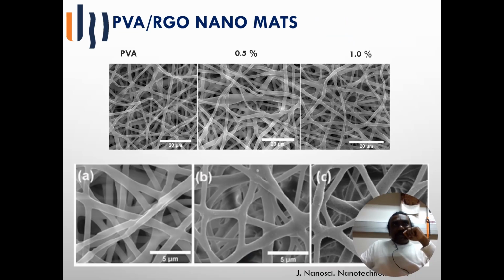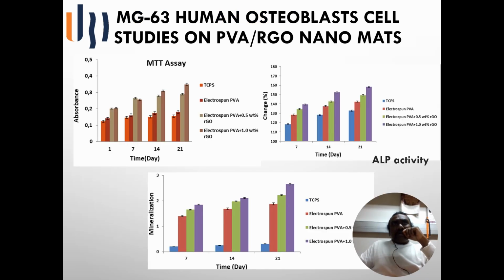Here, a different set of matrix, PVA and reduced graphene oxide nanomats. We have prepared them with only 0.5 weight% of RGO and 1 weight% of RGO. Here you have similar cell culture studies. Here you can see that 1 weight% RGO has shown very high cell growth even with the different stainings.